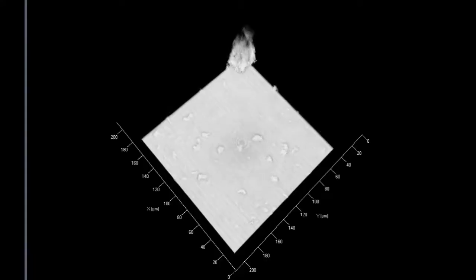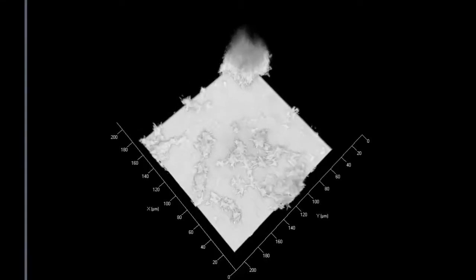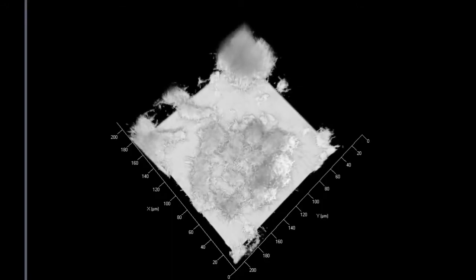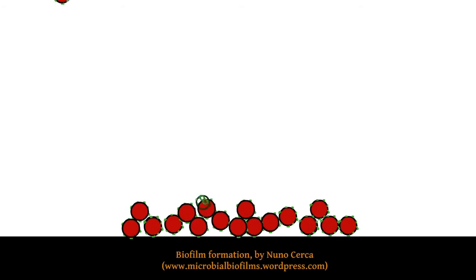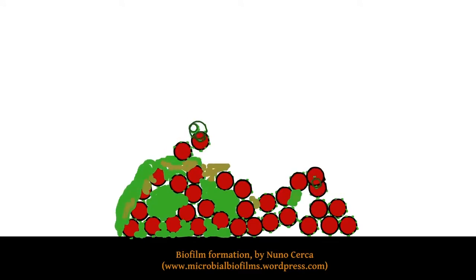Why avoid biofilm formation? All orthopedic materials are vulnerable to colonization by biofilm, including cobalt, chromium, titanium, polyethylene, PMMA, and ceramics. Also, it is known that initial adhesion triggers early biofilm formation, and the point of irreversible binding. The therapeutic point between both is named as window opportunity. At this point, bacteria are still susceptible to conventional antibiotics and immune responses. Consequently, avoiding adhesion to prevent bacteria colonization is something to take into account.